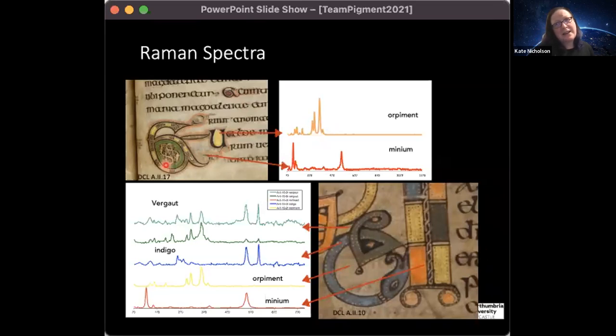And this is where Kate started to cry a little bit, because Raman spectroscopy is not good for every single pigment. There are two complications. One, fluorescence, a particular problem for organic pigments, things that don't have metals in them. And the other one, for pigments that really absorb your laser light and don't let it get back out again. And that was the problem with the green pigment on this page. So another technique is needed to find out and positively identify those.